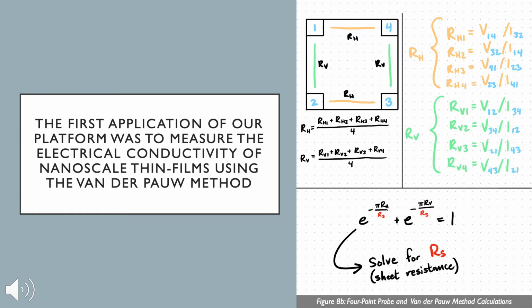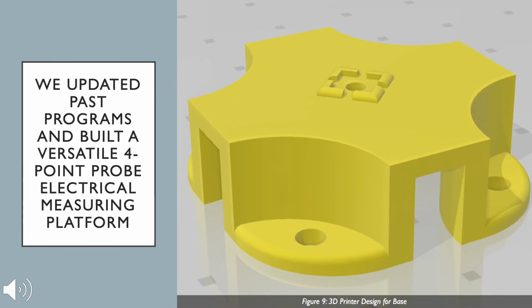Lastly, the basis of the 4-point probe method, which implicates van der Pauw's analysis to determine sheet resistance, includes: Step 1, determine the van der Pauw geometry to use. As stated before, from Figure 8a, we chose Part B, which has a square formation with probes on each corner. Step 2, alternate sourcing a current and measuring a voltage across adjacent corners of a square. And Step 3, calculate vertical and horizontal resistances separately, and determine sheet resistance from the van der Pauw equations using these resistances. With the supplies beginning to arrive, we began to organize and update past computer programs that would utilize the 4-point probe and van der Pauw methods to measure the electrical properties of composites.